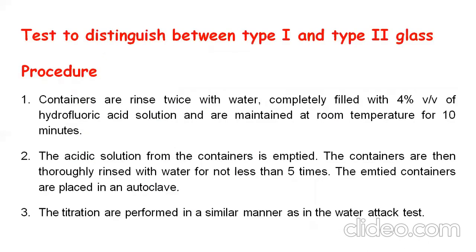Test to distinguish between type 1 and type 2 glass. Containers are rinsed twice with water, completely filled with 4% volume by volume hydrofluoric acid solution, and maintained at room temperature for 10 minutes. The acidic solution from the containers is emptied.